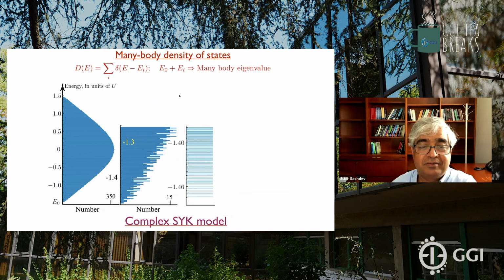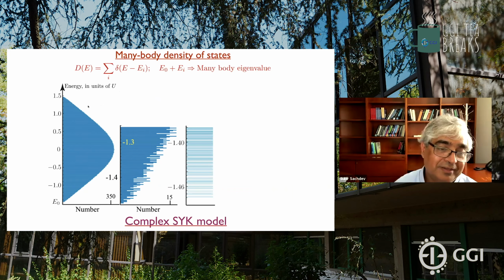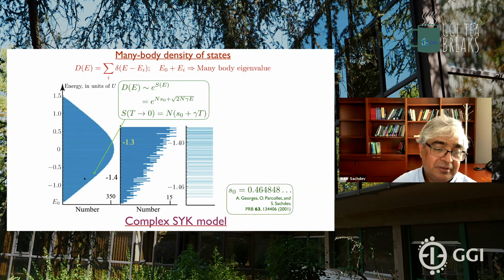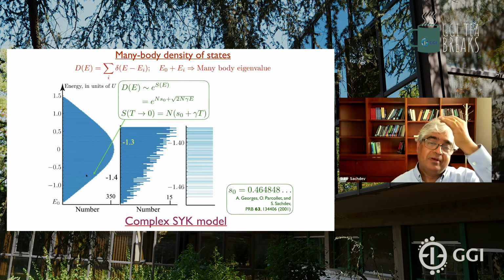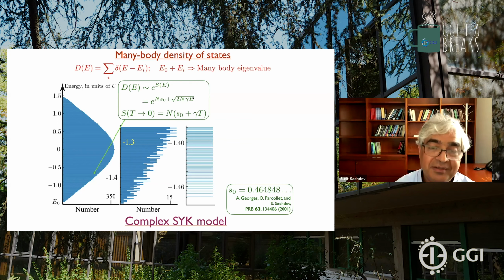Okay, so here I show you some numerical results of the many-body density of states. Now this is a system that's much, much more complicated, and this is what it looks like. So if you look at the density of states, somewhere not too low in energy, but the energy is extensive, then this is what you find. Now for the free electrons, you had this square root of NE number, and this is exactly what you get here. But now you get the surprise, and this is what was first deduced in this paper with George and Parcollet, you find that